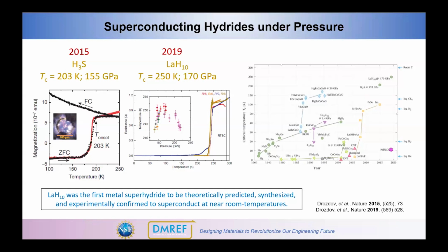So, superconductivity under high pressure. In 2015, superconductivity was discovered in this sulfur H3 compound with a TC of 203 Kelvin, but under a huge amount of pressure, 155 gigapascals. And then the lanthanum hydride in 2019 with a TC of 250 K, once again under enormous pressure. I pulled this plot off of Wikipedia or something like that. It shows the various TCs of various materials over the years. And as always, I'm disappointed they don't even put the organic superconductors on there, but we hopefully can change that.